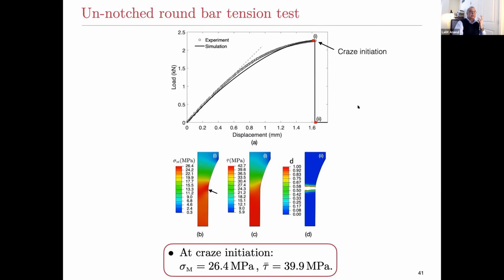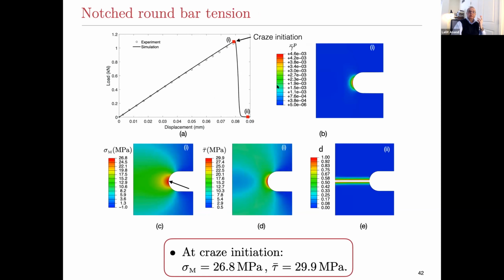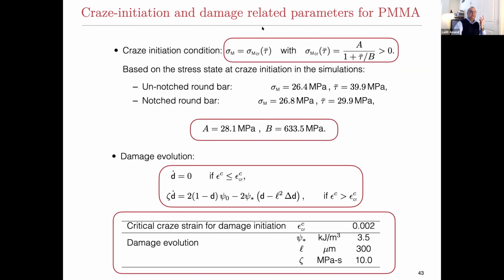Okay. You can do a similar thing in a notched round bar specimen. Again, there is plasticity at the notch root, but there you can also figure out what the mean normal stress is and what the shear stress is at craze initiation. And once you have these two sets of data, you go back to your craze initiation condition, and you can estimate now what that parameter A is and what that parameter B is. Okay. And then what you need is the damage evolution conditions. You need a critical value for the craze strain. Not much is known. We choose it to be a small number, 0.2%. Maybe it's too large, I don't know, but it's fine.